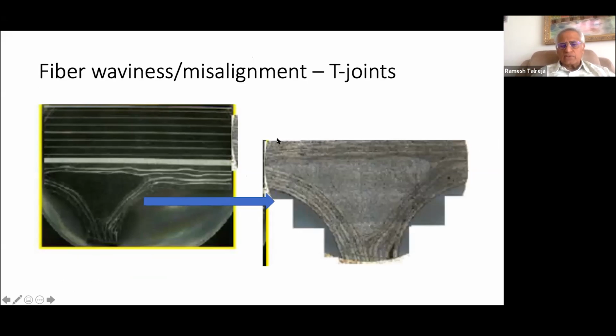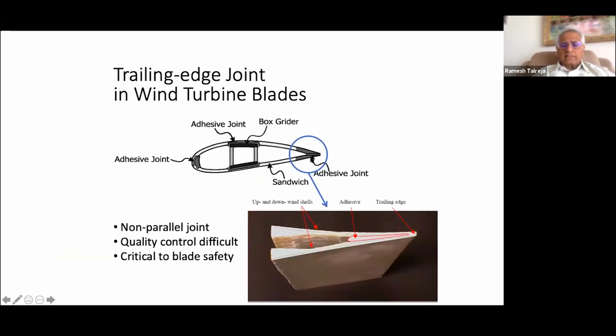Joints are, adhesive joints, as you know, are common in composites, and often the thermal expansion mismatch between parts that are being joined together can lead to waviness of fibers close to the interfaces. So you see that's the situation here, and the close-up picture also shows this. So this is, say, some airfoil. An example is taken from wind turbine blade. You can see the joints are typically in the leading edge, trailing edge, and between the spar, which in this case is the box girder, and the shell.